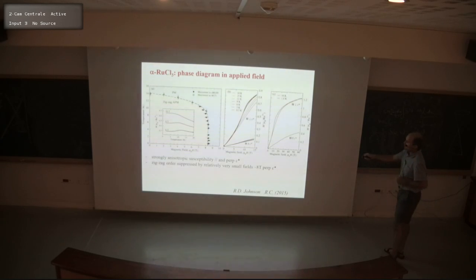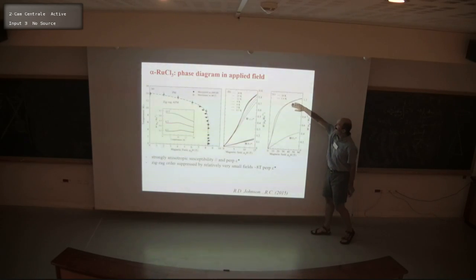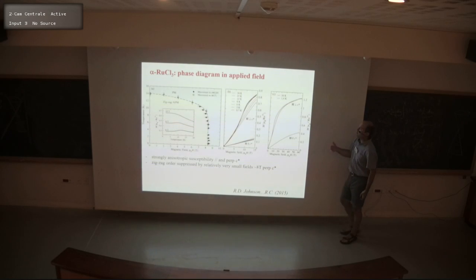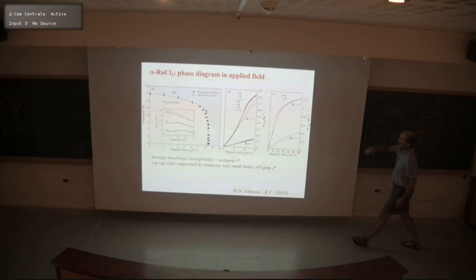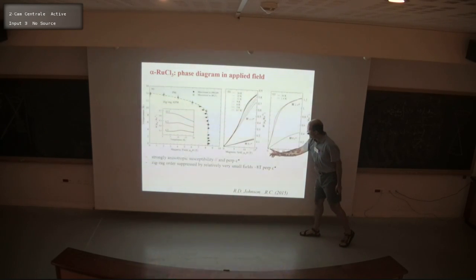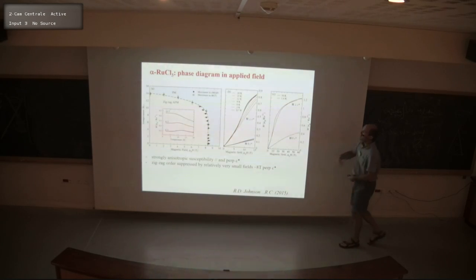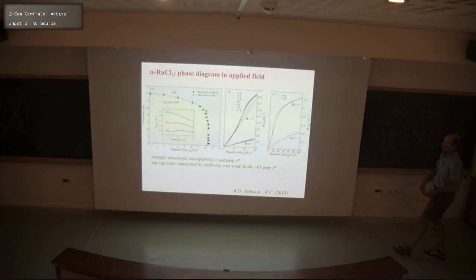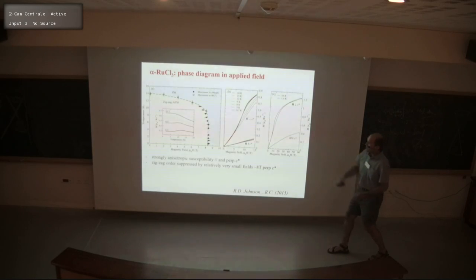So what's important to appreciate here is that 8 Tesla is still a field that's way below saturation, in a sense that here magnetization measurements done in pulse fields up to 60 Tesla, and the magnetization is still increasing. Of course, only asymptotically, as you expect in a system with a non-conserved spin, but still from 8 Tesla to this, there's a wide regime to continue to quench quantum fluctuations. So the region immediately above the transition still has a large moment available to quantum fluctuate that's not ordered.